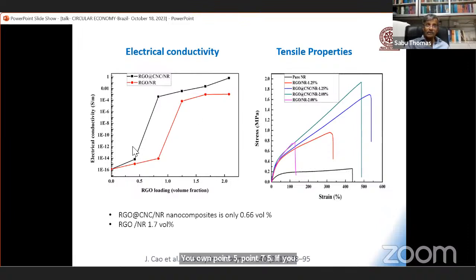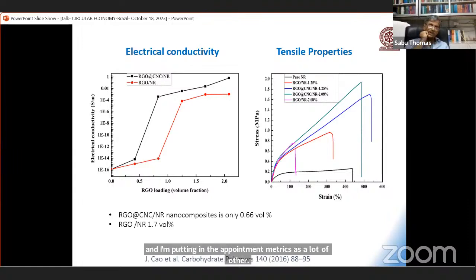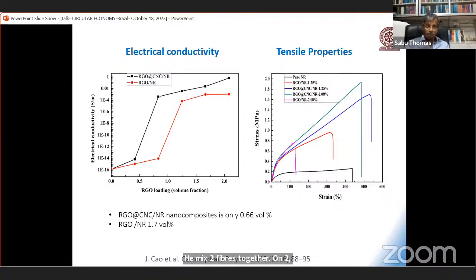But if you combine both RGO and cellulose nanocrystal, look at this. The percolation is shifted to lower concentration of RGO. This is something interesting. And then another important data I want to tell you, these hybrid system, this is pure NR. These hybrid system show very high mechanics. Hybridizing RGO and nanocellulose together and putting into a polymer matrix has a lot of relevance. If you mix two fibers together, two nanomaterials together, you get better dispersion in the polymer matrix.